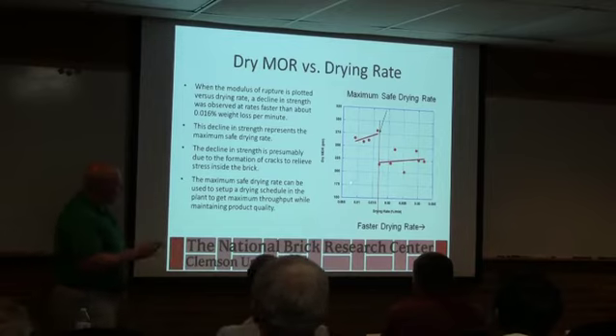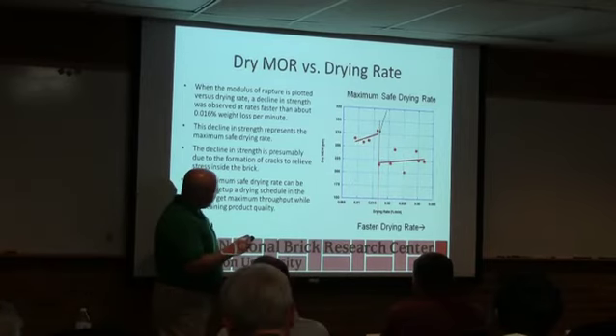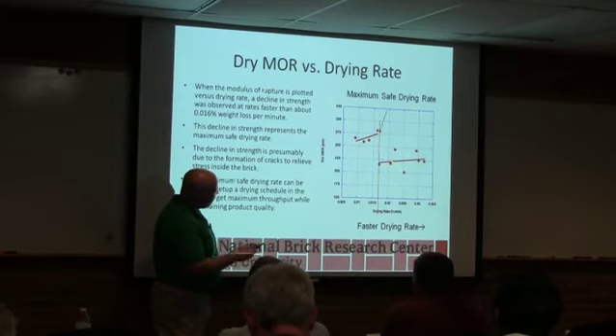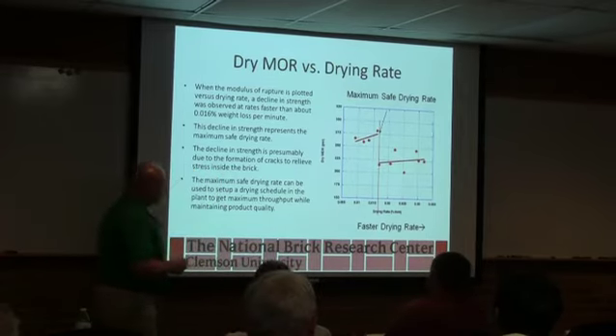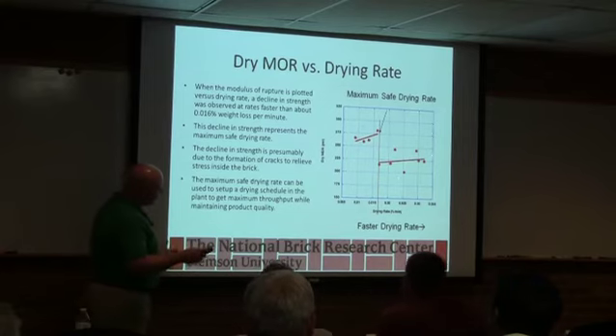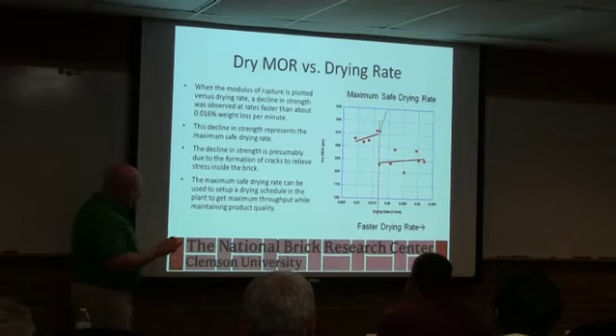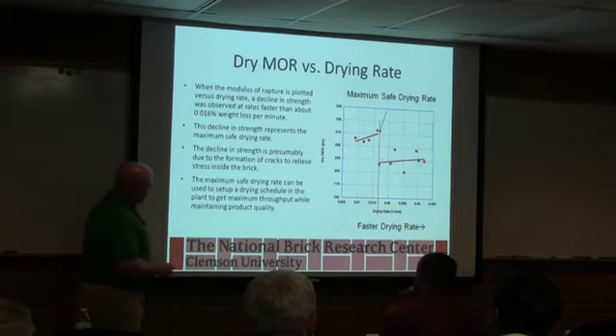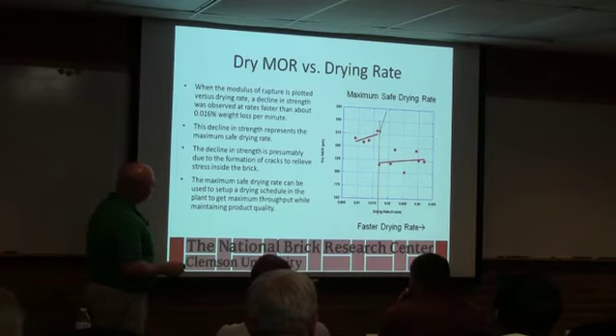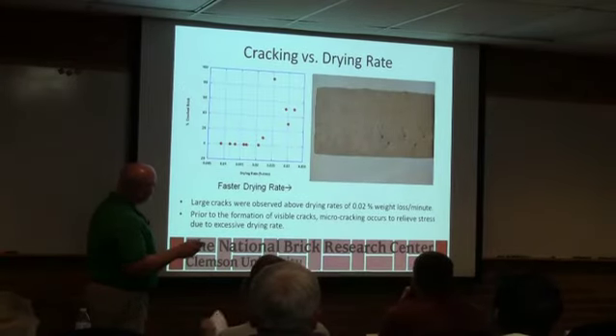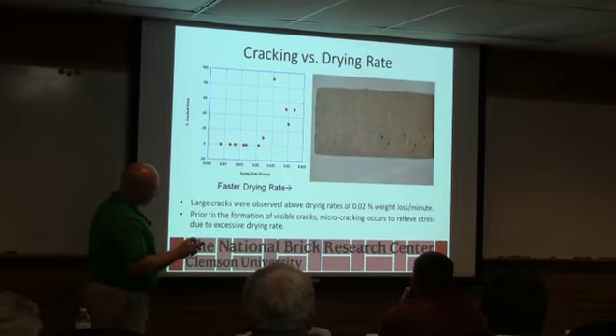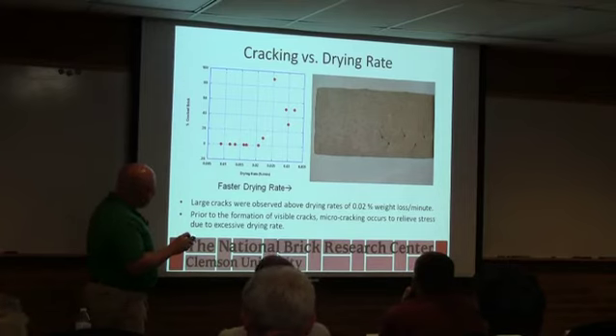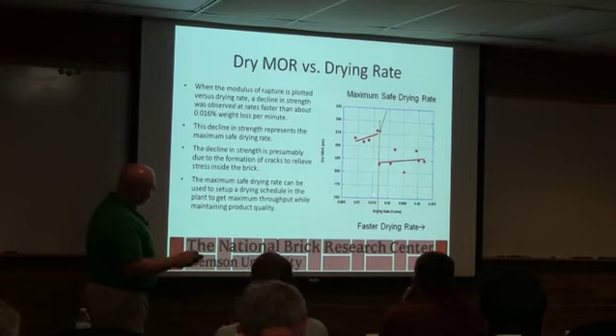So what we did with ours is we were doing dry modulus of rupture, and we were looking at increasing drying rate. So we see strength coming along, and then there was a drying rate where we definitely saw a fall off in the strength, and the scatter went up a lot. And presumably it's because we're making cracks inside the brick because we're pushing the water too fast, and it's causing damage to the pores. We tried to also look and see if we could visibly see the cracks, and we had to get to a lot higher drying rate before we could see the cracks, whereas the modulus of rupture picked up that these are not the same brick.